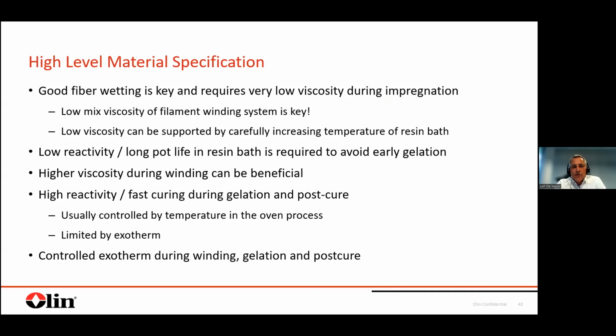And then basically the higher viscosity during winding, this can be a beneficial aspect. It can be managed by running the temperature profile. It can also be managed by choosing the proper resin hardener combination. And in the end, in the final steps, in the gelation and post-cure, it's everything about reactivity. How fast do you build up the cross-link density, the molecular network, at which temperature is required to get there. And this is also where we have a range of different resins and hardeners to choose from, and where we can support to find the right balance.